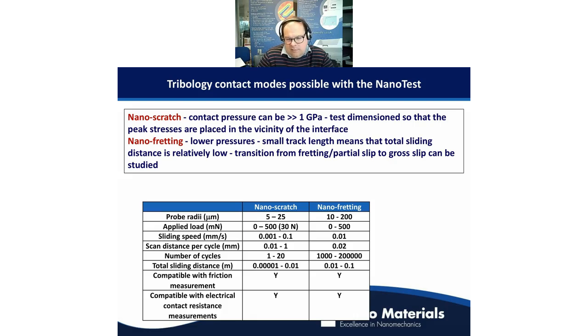Okay, so here in this test, it's a reciprocating wear test. The probe will be sliding backwards and forwards rapidly, high frequency over the same track length, and that simulates a different type of real world contact scenario. Okay, so it's not an overload test like scratch testing can be, ramp load scratch testing, loading up until we get a failure. It's a subcritical loading, and it's more of a wear and fatigue type test.